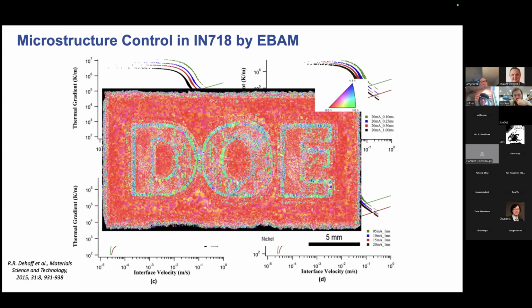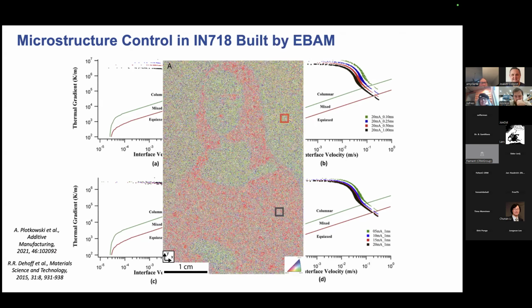So this is an example where they crystallographically spelled out Department of Energy, or DOE, in the microstructure by turning on and off the columnar to equiax transition during processing, which is actually pretty cool. And a more recent update on this comes from Plotkowski et al. Here they've actually made the Mona Lisa in the microstructure by turning on and off columnar to equiax transition, which is pretty neat. But it really illustrates your ability to, again, control microstructure development during processing by understanding the conditions being employed.